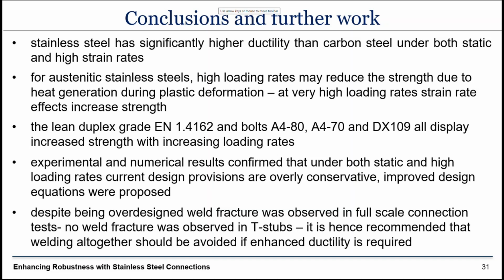The conclusions we reached from the project is that stainless steel has significantly higher ductility than carbon steel under static conditions and under high strain rates, although that advantage diminishes a bit with strain rate. For austenitic stainless steels, high loading rates may reduce the strength due to heat generation during plastic deformation. So it is not safe to say just use the static material properties, because you may get a small reduction up to 6-7% in ultimate stress.